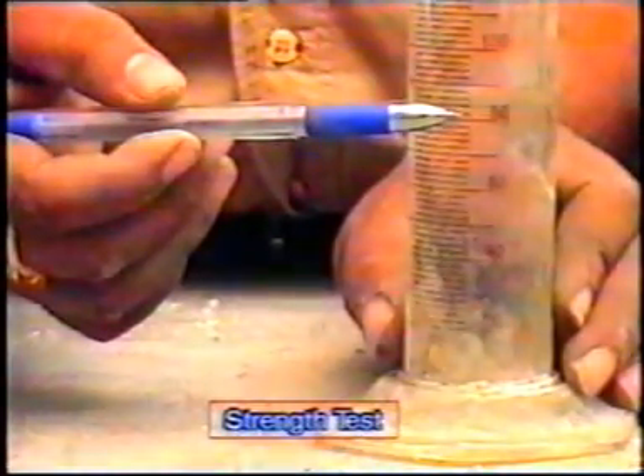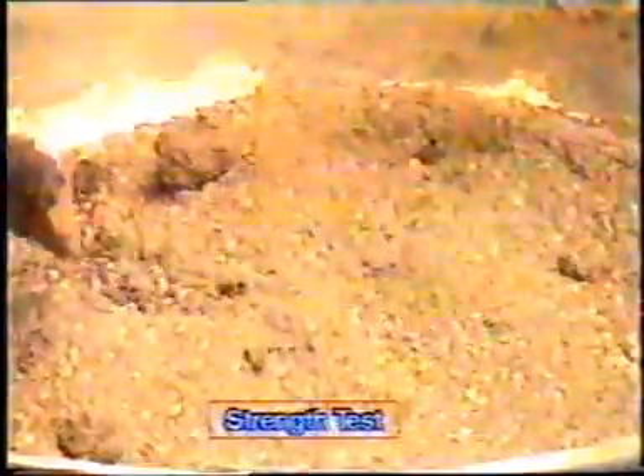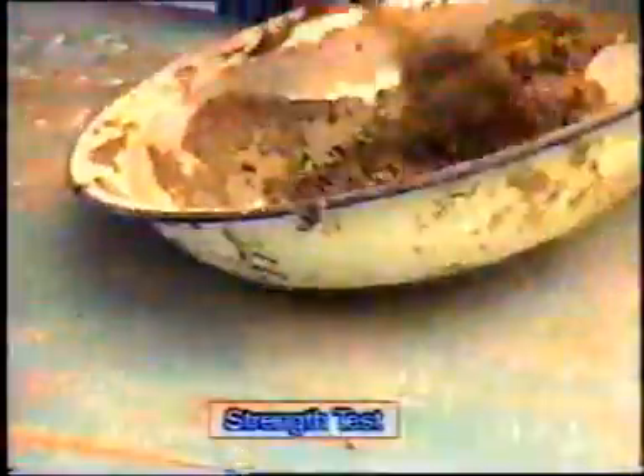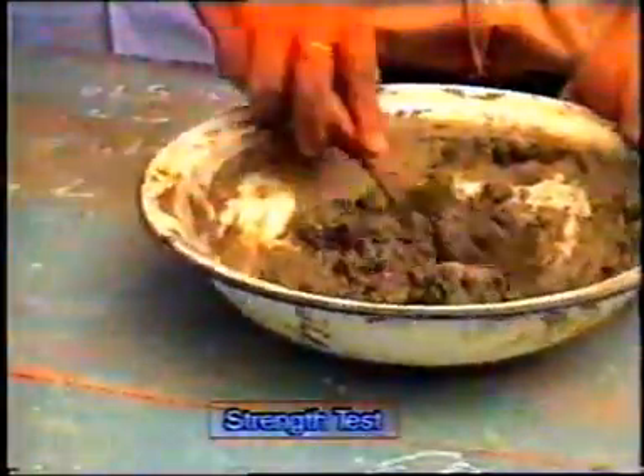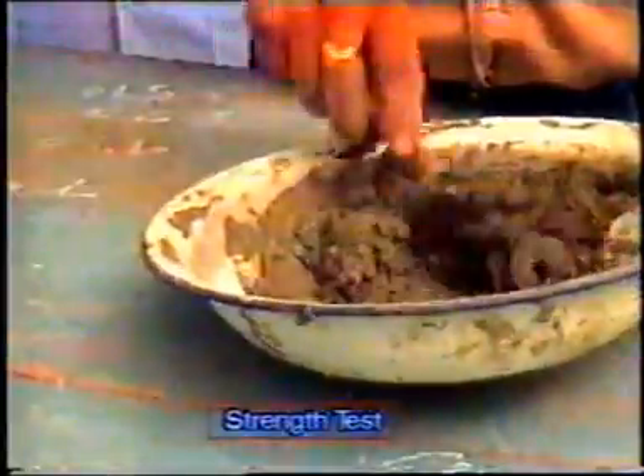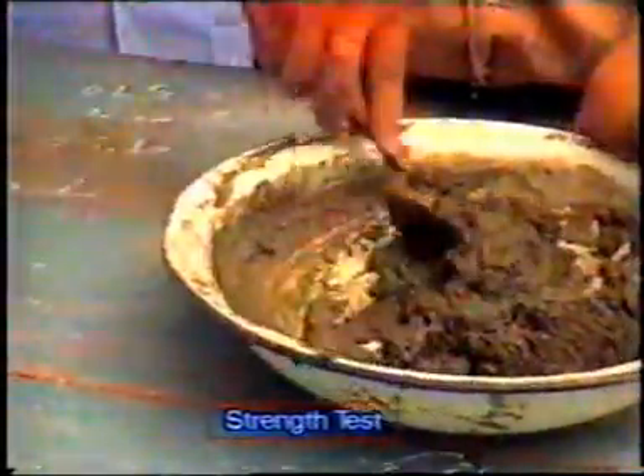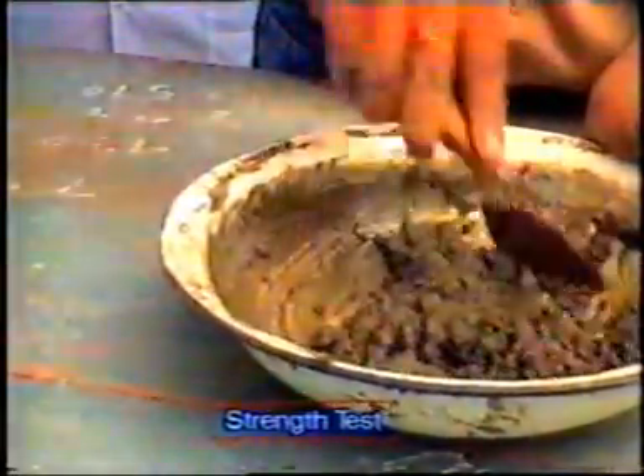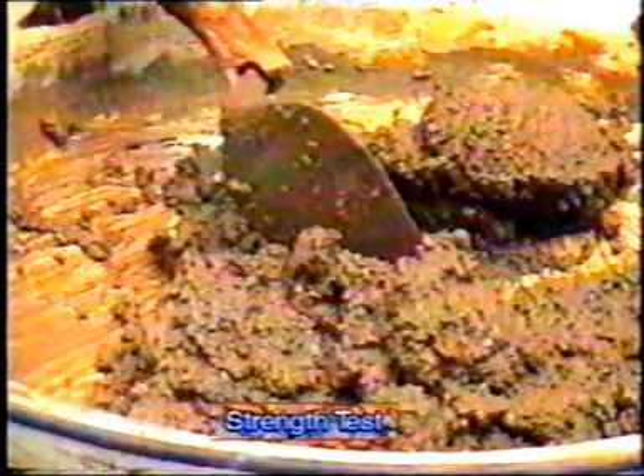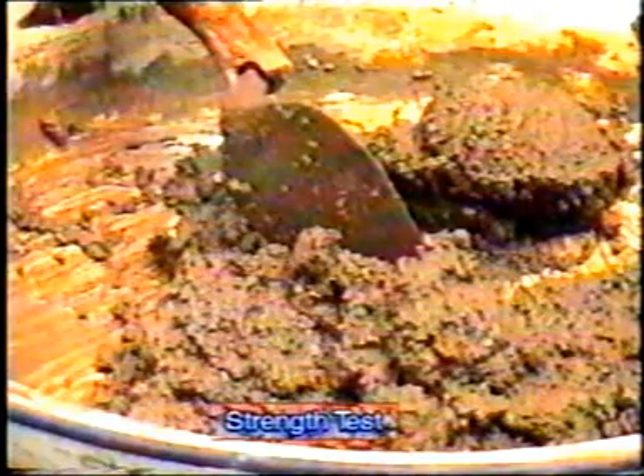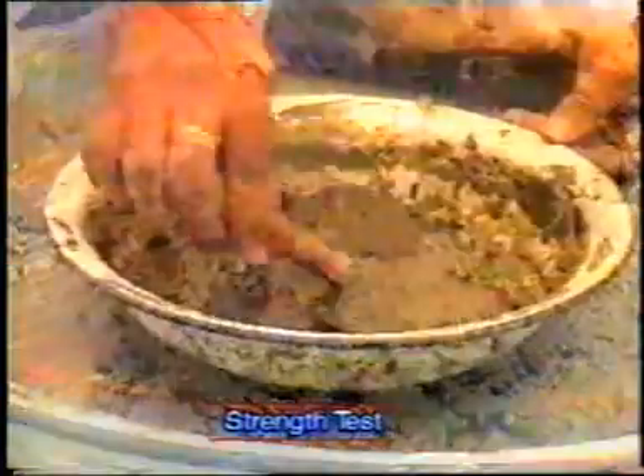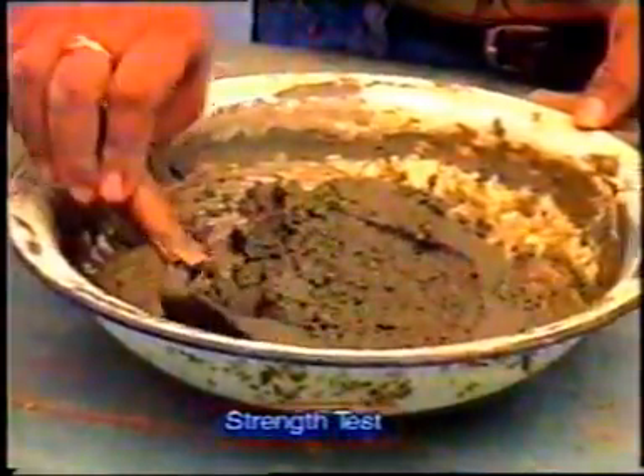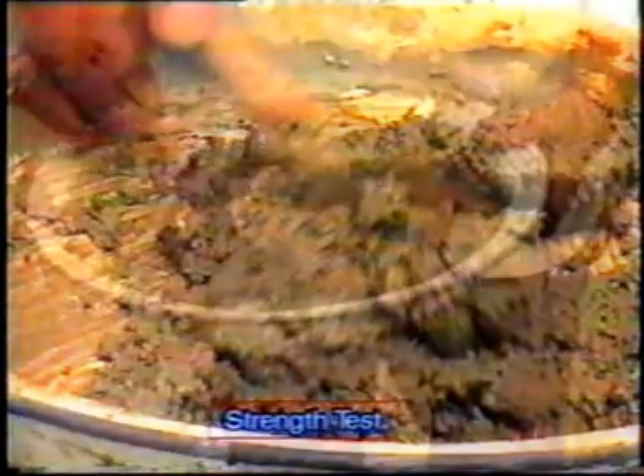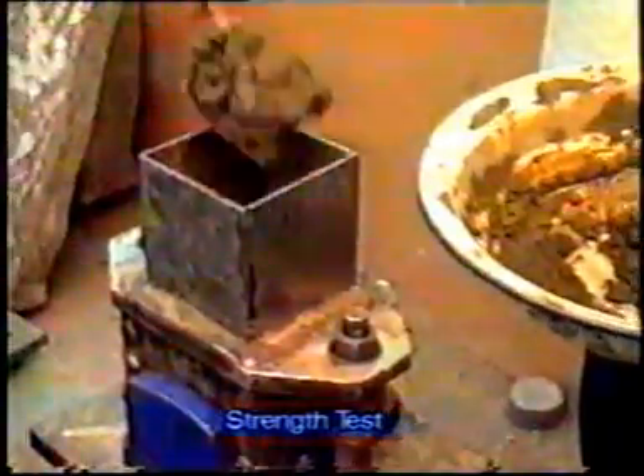Quantity of water to be added will be P by 4 plus 3% of combined weight of cement and sand, where P is percentage of water required for normal consistency. Mix it thoroughly to get uniform paste. This process of adding water and mixing to get the uniform paste should be completed within 4 minutes from the addition of water to the cement, and this should be conducted at 27 degree centigrade temperature.